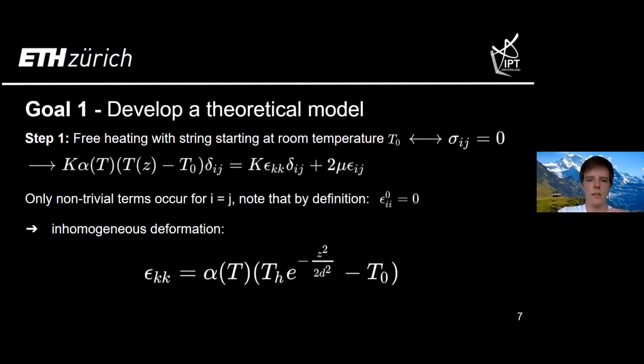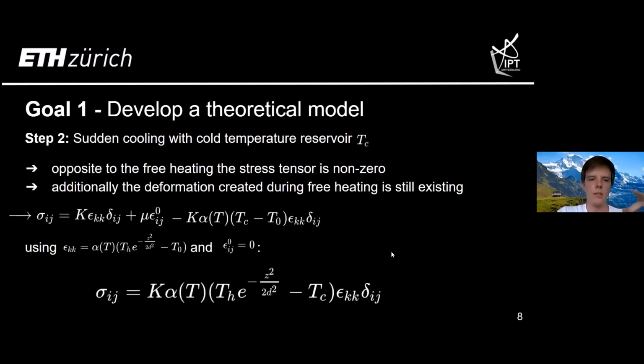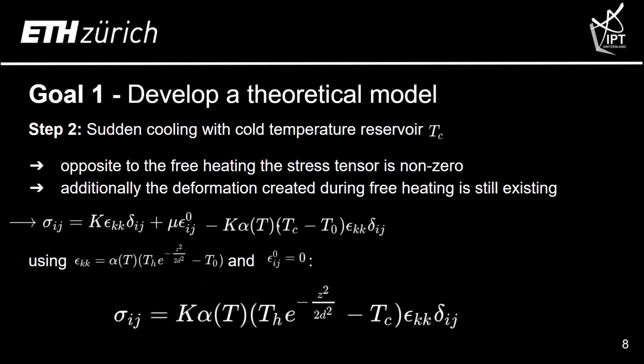I stated that because of the sudden cooling, the deformation of the heating is still present. And additionally to that, we have a second term, which is the Tc, the contact with the cold temperature, which adds an additional deformation from the cooling. And this results in this expression here below. This is our tension in the bottle after we heated it and placed it into the cold reservoir. It is proportional to the hottest and coldest temperature, and you can also see the stress distribution is not uniform, since it also depends on the Gaussian function of the temperature distribution in the beginning.